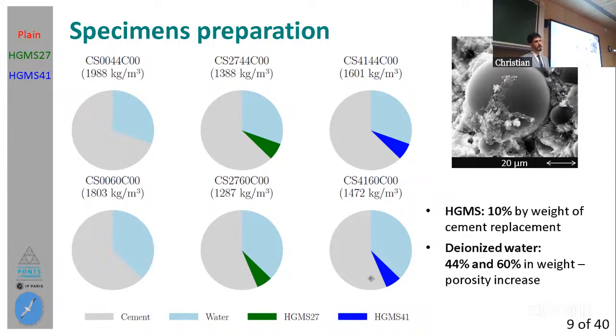So yes, as you mentioned, I have used superplasticizer in these two specimens. I used it, I think, at 0.2 and 0.3% by weight of cement. The actual answer is that no, I didn't consider any effect that superplasticizer could have on the cement matrix microstructure. I only added it to make it possible to mix these mixtures, because I was adding 10% by weight of these spheres, and since they are very light, it's a huge amount in volume. It's like 50% volume spheres and 50% volume cement. So it was necessary to add it to make it possible to mix the slurry.